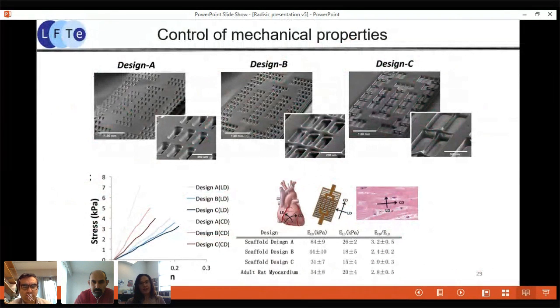Through the 3D stamping technique, one really nice feature is that we can control apparent mechanical properties of this entire scaffold. So we really do have multiple levels of control of tissue properties. The first level of control is through polymer chemistry. And then we create material that has tunable properties. Then we could go from 50 kilopascal of real Young's modulus to over 1500 kilopascal.